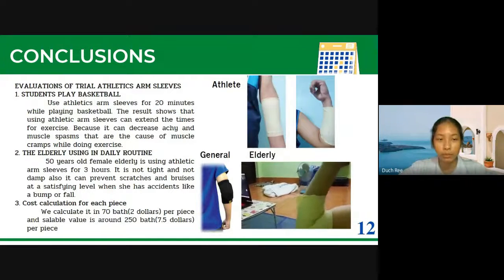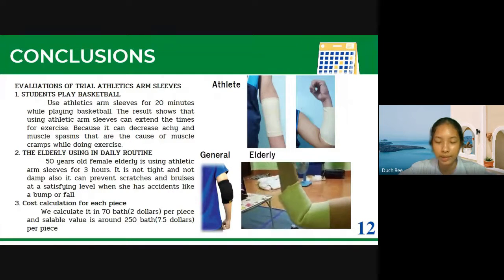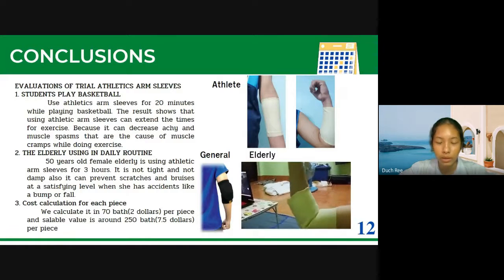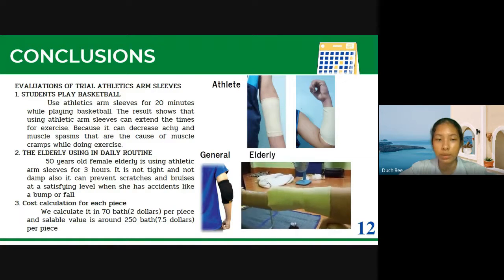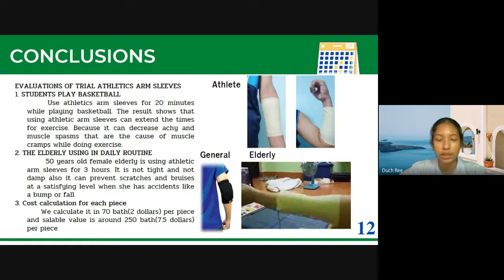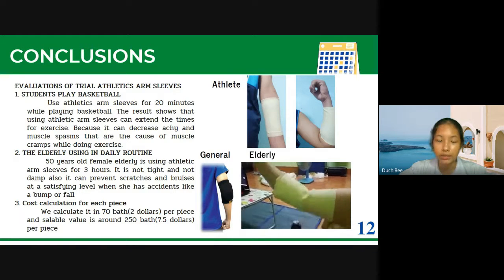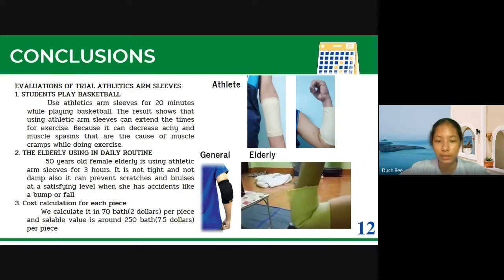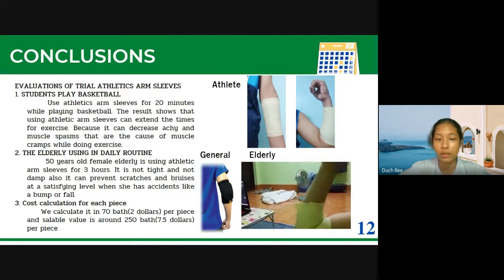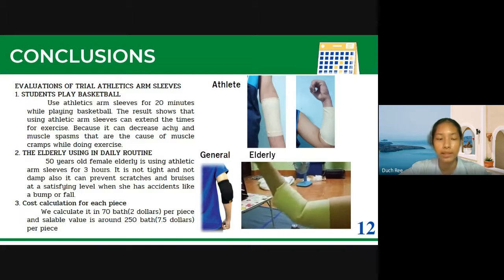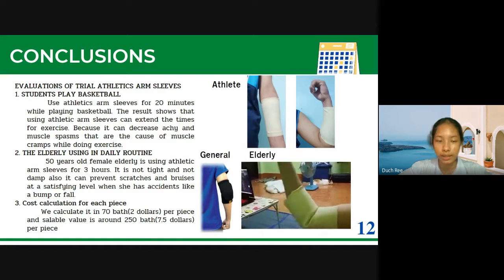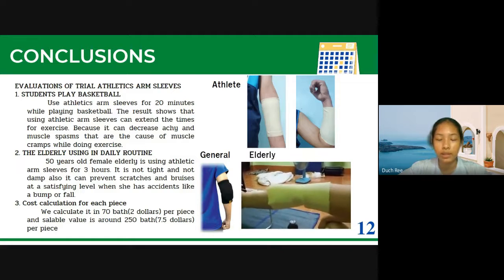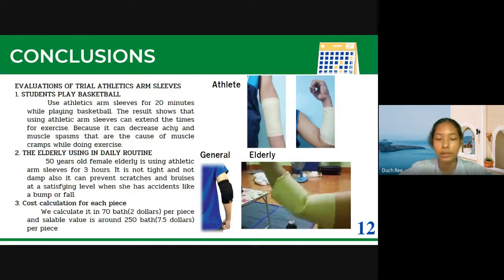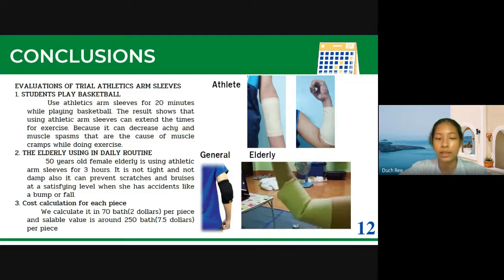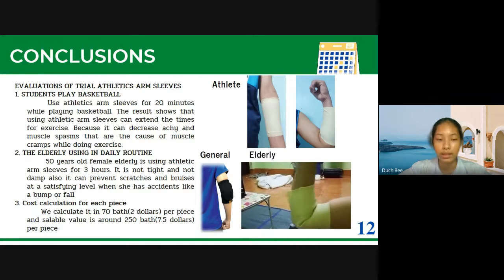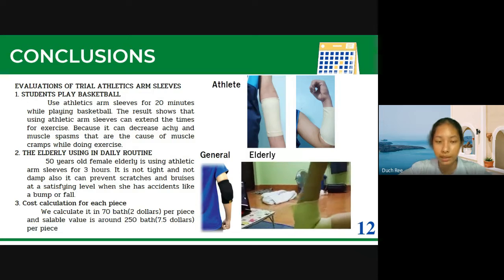Now, I'm going to talk about evaluations of the athletic arm sleeve. First, students play basketball, using the athletic arm sleeve for 20 minutes. The results show that using the athletic arm sleeve can extend the time for exercise because it can decrease achy and muscle spasms, which are the cause of muscle cramps while doing exercise. Second, the elderly using it in daily routine. A 50-year-old elderly female used the athletic arm sleeve for 3 hours. It is not tight and not damp. Also, it can prevent scratches and bruises at a satisfying level when she has an accident like a bump or fall.